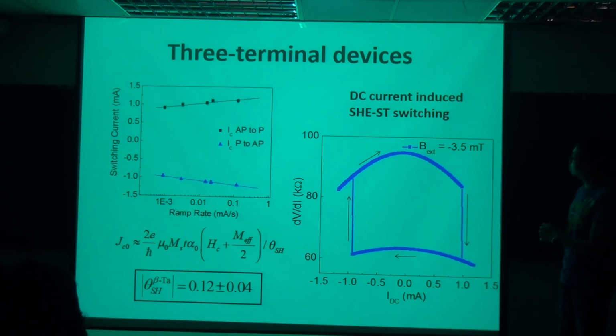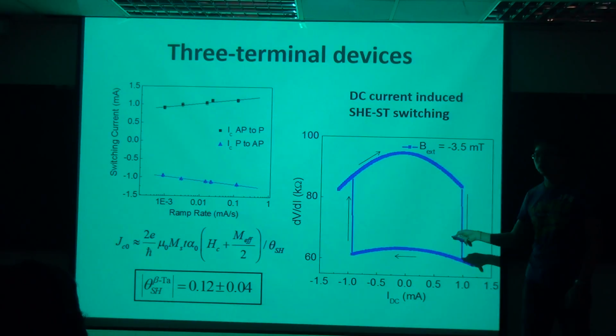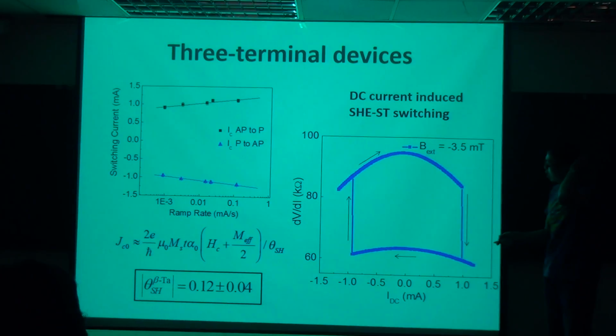And in order to determine the critical switching current density from the switching curve, the switching diagram, we use the formula that I just showed in the first part of my talk. And we only replaced the spin polarization P with spin-Hall angle. So like I said, the spin-Hall angle is the efficiency of generating spin, so it's like the value P that I just mentioned. And using this and the data I just showed here, we can estimate from the switching measurements that the spin-Hall efficiency of beta tantalum is about 12%, which is pretty close to the 15% I just mentioned. But this is actually negative 12% because the sign is negative.